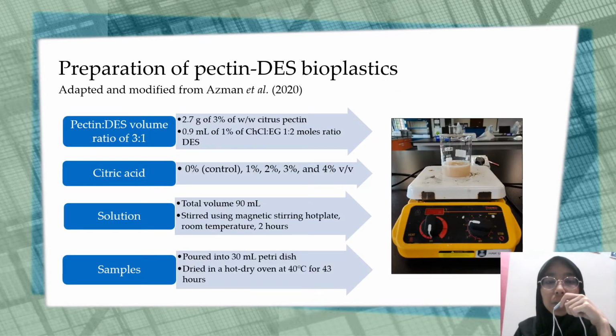2.7 grams of 3% weight over weight citrus pectin and 0.9 ml of 1% DES were added with varying concentrations of citric acid to obtain a 90 ml bioplastic solution, which was stirred at room temperature for 2 hours. This solution was poured into a 30 ml petri dish and dried at 40 degrees Celsius for 43 hours.